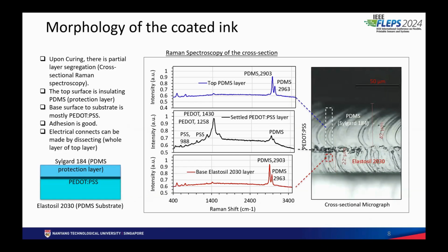Talking about the morphology of the ink, I think it's not so straightforward. When we coat and cure the ink, what we found is that there is some kind of layer segregation. The top layer becomes the insulating protective PDMS layer, and the interfacing layer to the substrate is actually the conducting layer of PEDOT:PSS, and then the base layer is our substrate. How we found this out is by doing cross-sectional Raman spectroscopy, and we could tally the peaks of the cross-sectional spectrum with the PDMS, and here with the PEDOT, and this is just the substrate material. We also found that there is some form of seepage of PSS into the PDMS layer, but only at the interface.